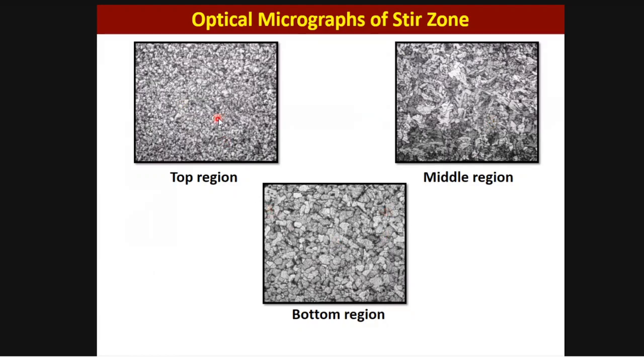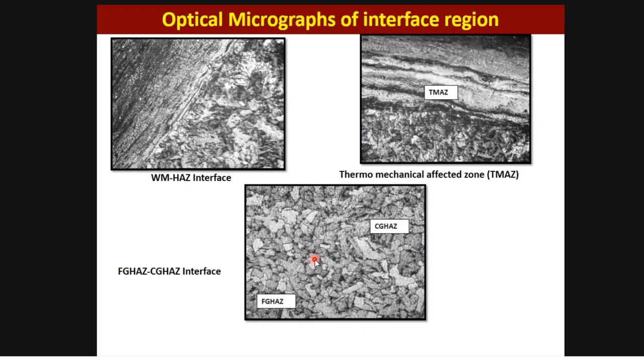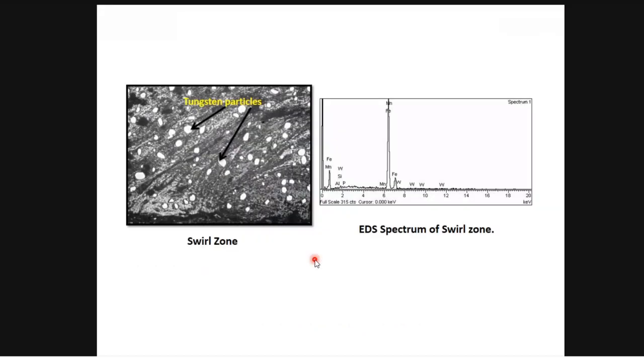Even this thickness is 5 mm thickness. It's only 5 mm thickness. The plate thickness is 5 mm. Within 5 mm, there is a change in the microstructure. And this is the heat affected zone interface microstructure. And then we went for the SEM and EDS analysis.